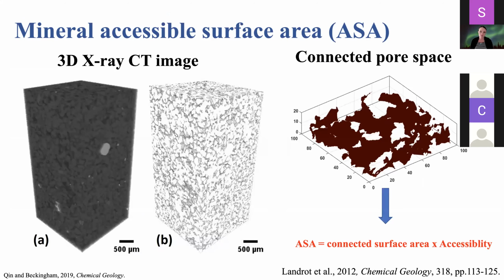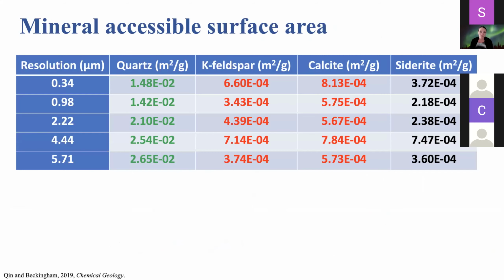We also accounted for pore connectivity in 3 dimensions using our 3D X-ray CT imaging, and then used that to quantify accessible surface area. And so what we saw is that you have an increase in the accessible surface area of quartz with decreasing resolution, and decreases in the accessible surface area of potassium feldspar and calcite. But one thing to also notice is that these variations are less than 1 order of magnitude.